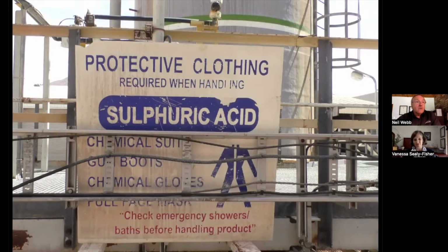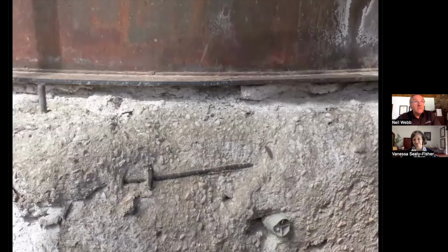And we not only are dealing with atmospheric conditions, but often we have concrete structures that are used to provide chemical dams, if I can call it that. So in the parlance, it's known as a bund. It's an area where the tank that contains the material that you're dealing with, if it fails or leaks or for whatever reason, you need to prevent that liquid from flowing out into the environment, never mind what other damage it may cause. And you can imagine if you allow sulfuric acid to come into contact with concrete, well, you're going to land up with no concrete. And not only sulfuric acid, here's a situation where we had concentrated caustic in contact with the concrete.